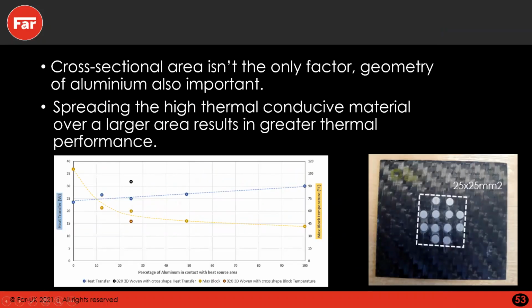So we also found that the cross-sectional area of the thermal conductive material isn't the only factor influencing this. The geometry of your high thermally conductive material is also important. So the picture of the coupon shows 12 4mm diameter rods, which the total area of them is equivalent to 25% of the heat area. By spreading the same amount of aluminium out over the heat area, we can achieve greater results without increasing our weight. You can see on the graph the two bold data points. We have a lower heat source temperature and a greater heat flow.